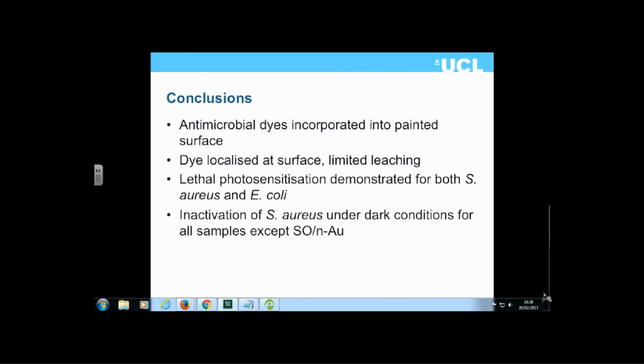So, in conclusion to this part of the talk, I've covered antimicrobial dyes and incorporating them into surfaces, dye localization at the surface and leaching, and lethal photosensitization for both Staphylococcus aureus and E. coli—showing that it works both in the light and under dark conditions, which was a surprise.